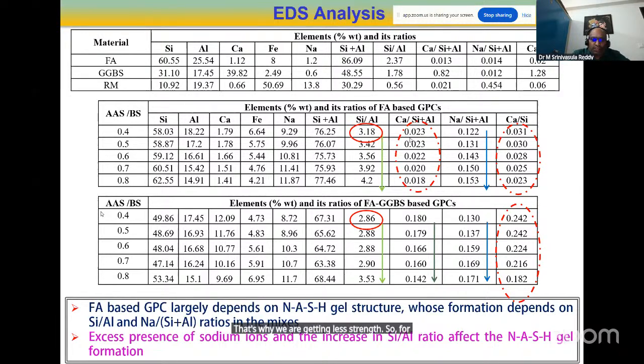For a high ratio of Ca, more amount of Ca means we are getting other products like C-A-S-H and C-S-H. Because of this, we are getting good strength. Even with fly ash or fly ash GGBS, there may be very little C-A-S-H formation with fly ash alone, because my calcium is maximum 1% only. So maybe you can ignore this, but still you can observe that the decrease in the ratio is affecting the strength. Again, with the increase in the Si to Al ratio, more aluminum will also hinder. So you can notice the same thing here. With the Ca by Si plus Al decrease, we are observing a decrease in the strength. With the increase in the Si to Al ratio, we are observing a decrease in the strength, and also with the increase in the Na to Si plus Al ratio, we are observing that.